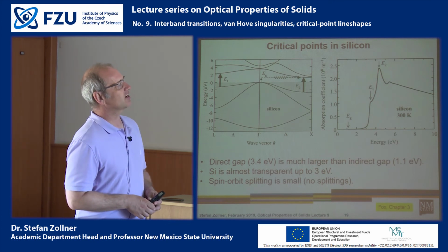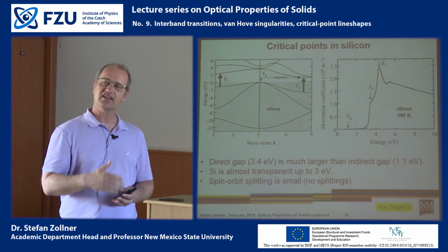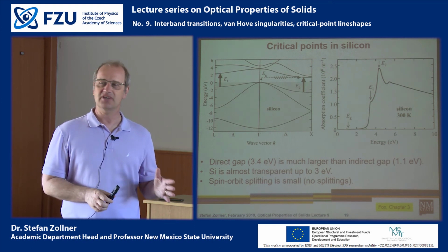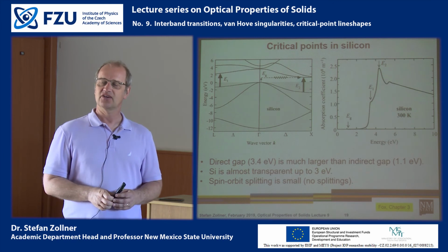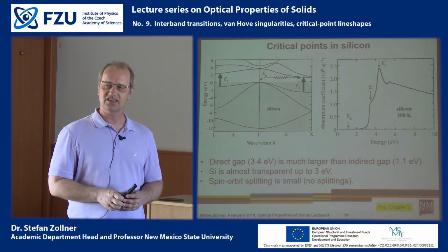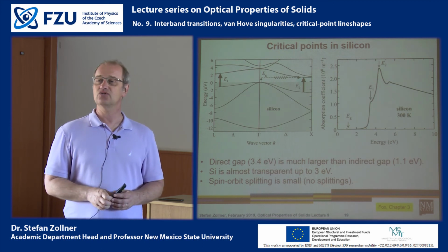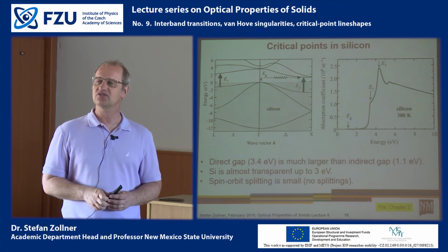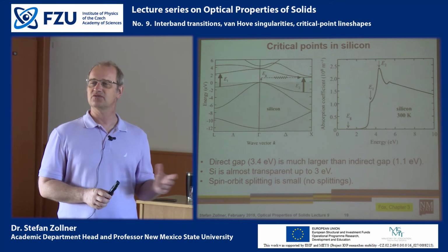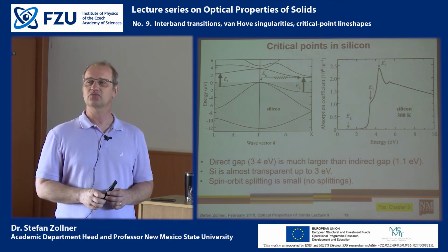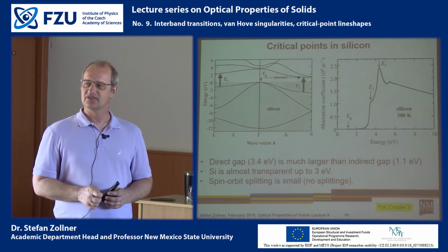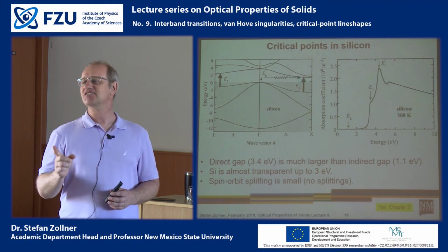If you want to measure at higher energies, let's say between 10 and 20 electron volts, then there can no longer be any windows in the beam path. You probably need to go to a synchrotron as the light source. And you need to use all reflective optics, which means that your polarizer consists of typically three gold mirrors or three magnesium fluoride mirrors at glancing incidence.